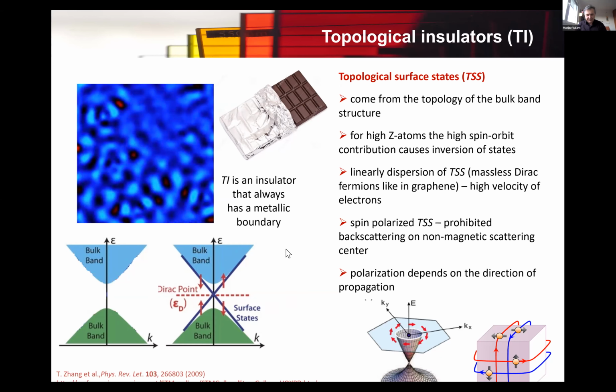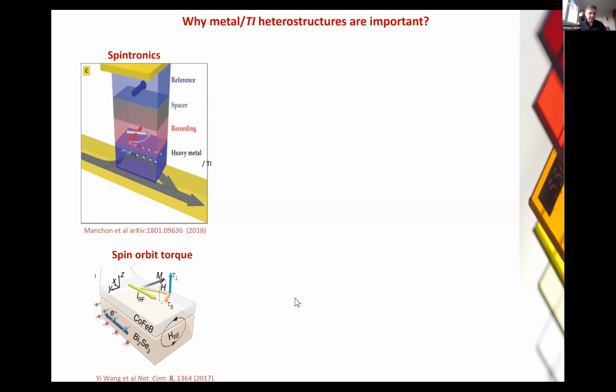Now, these electrons have very high velocity. You can see that these topological surface states are linearly dispersed, and they are very similar to the Dirac fermions in graphene. So for that reason, such systems would be very useful for high velocity electronics. In addition, the electrons are spin polarized, and the spin polarization depends on the direction of the propagation. So consequently, all the spintronic technology is interested in this material. There are a lot of foreseen applications. One interesting one is, for instance, spin valves, where you actually can switch magnetization without a magnetic field, just by applying a polarized current, and the spin orbit torque will take care of the switching of magnetization.